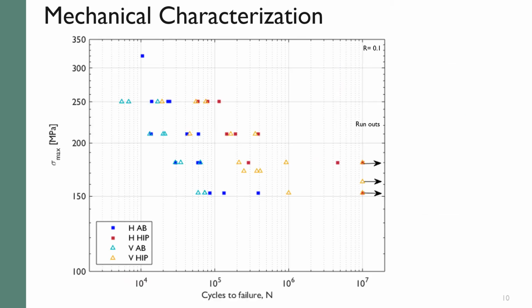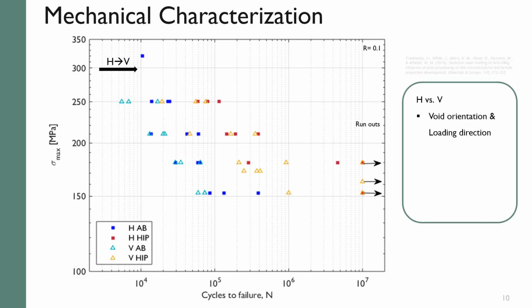Here you can see the S-N fatigue test data for horizontal and vertical samples in as-built and HIP condition. Overall, horizontal samples, which are represented by the squares, are located more towards the right, showing better fatigue resistance as compared to the vertical samples, which are shown by the triangles. This can be explained by the void orientation being perpendicular to the loading direction in the vertical samples.